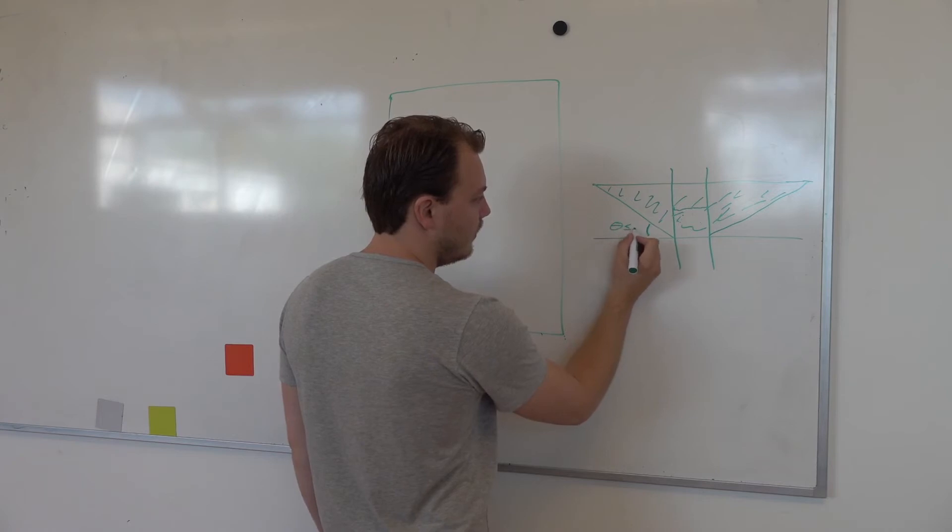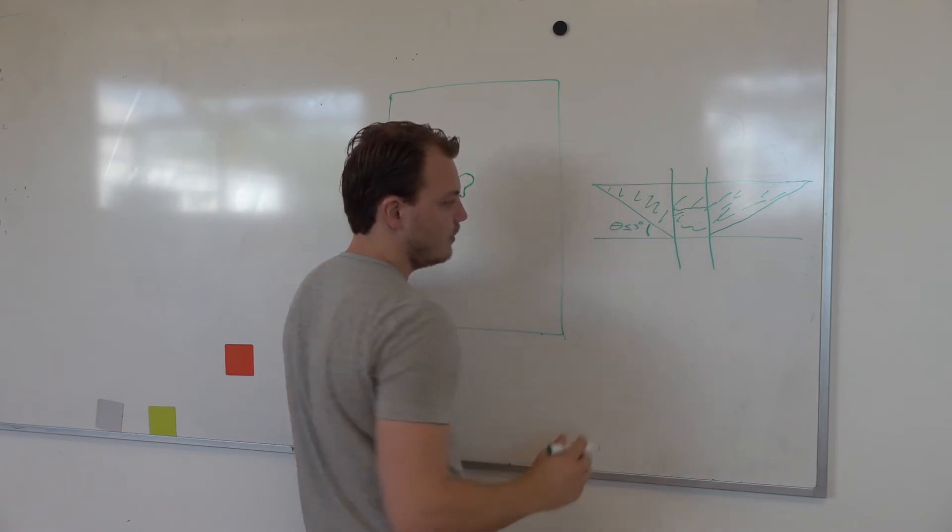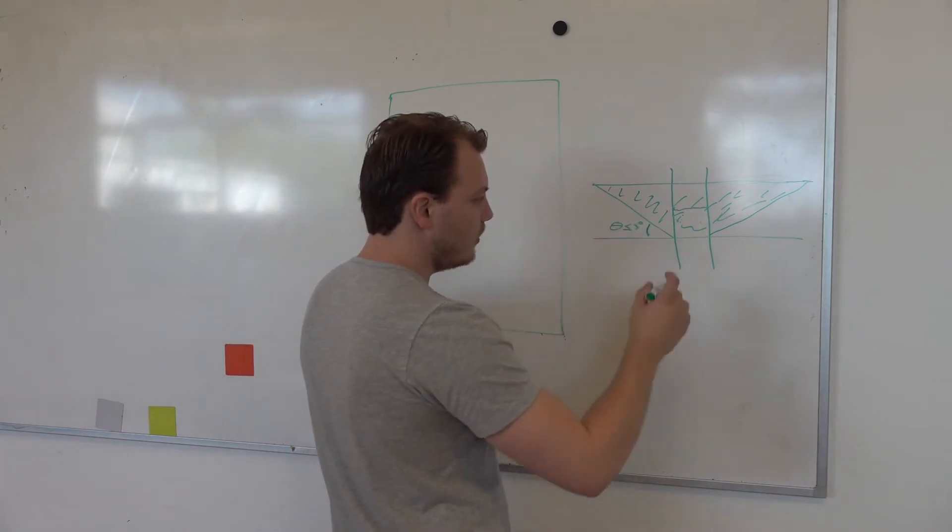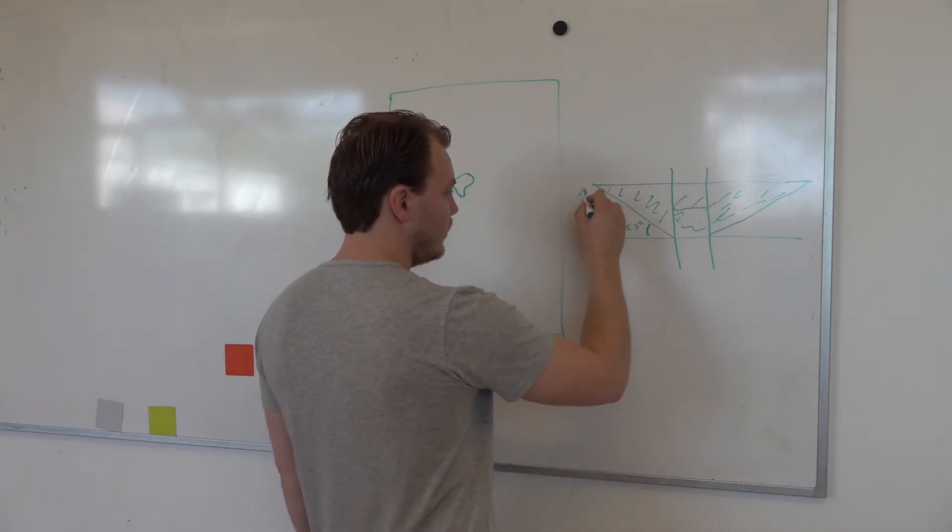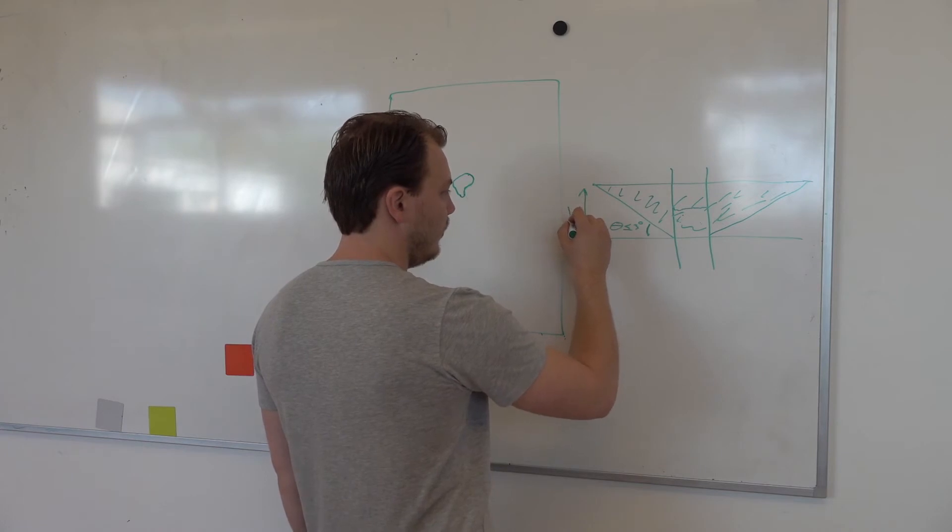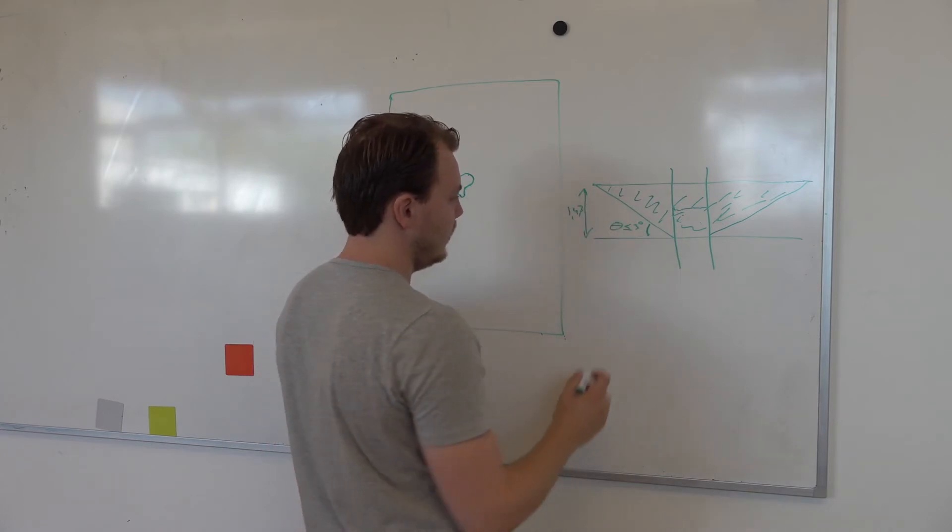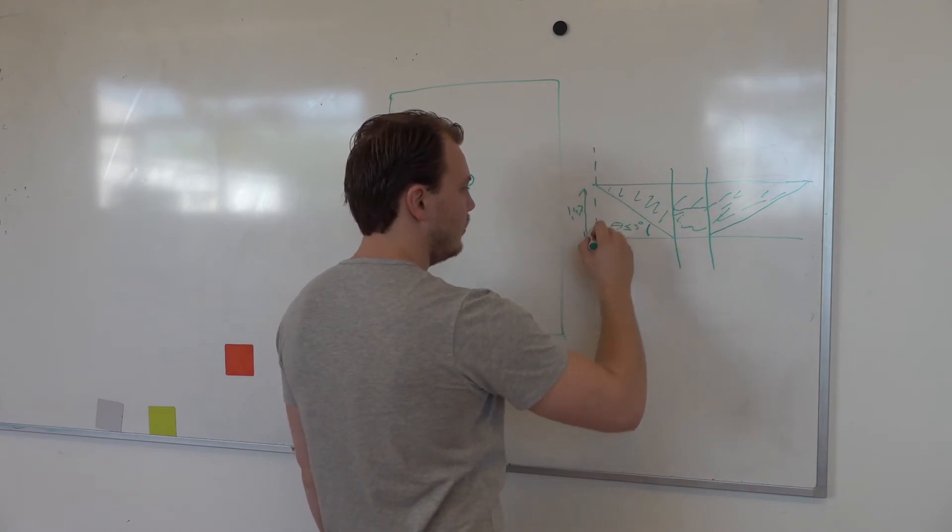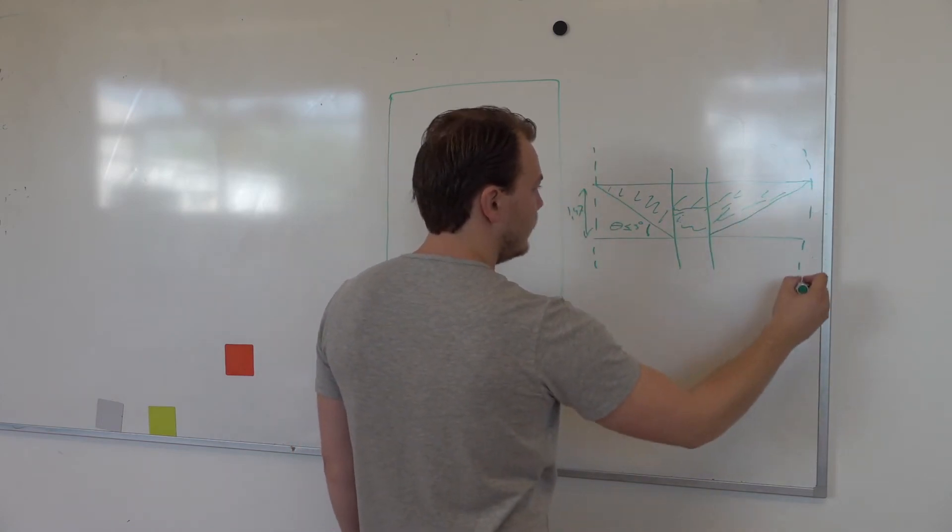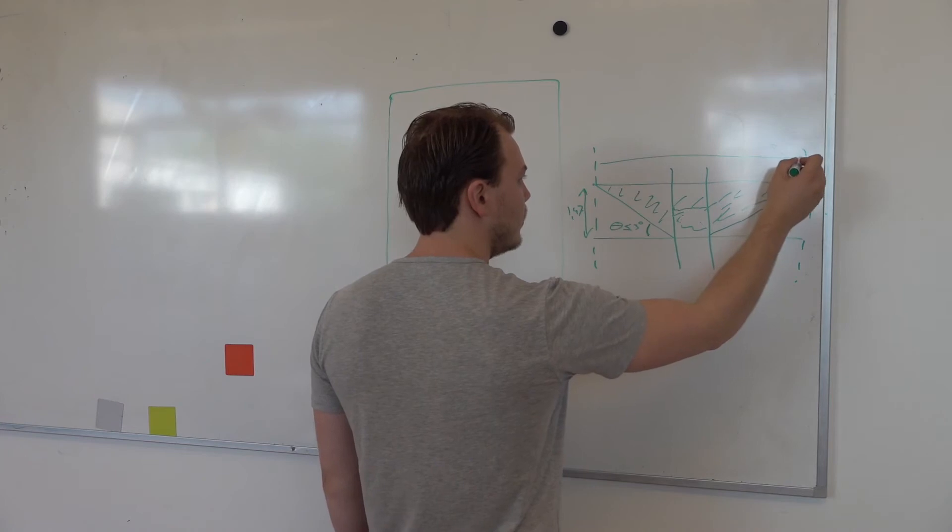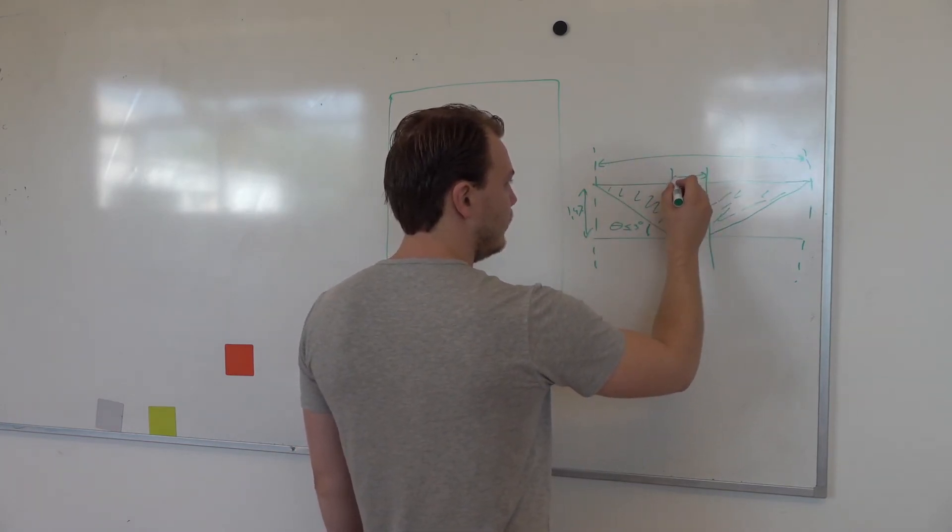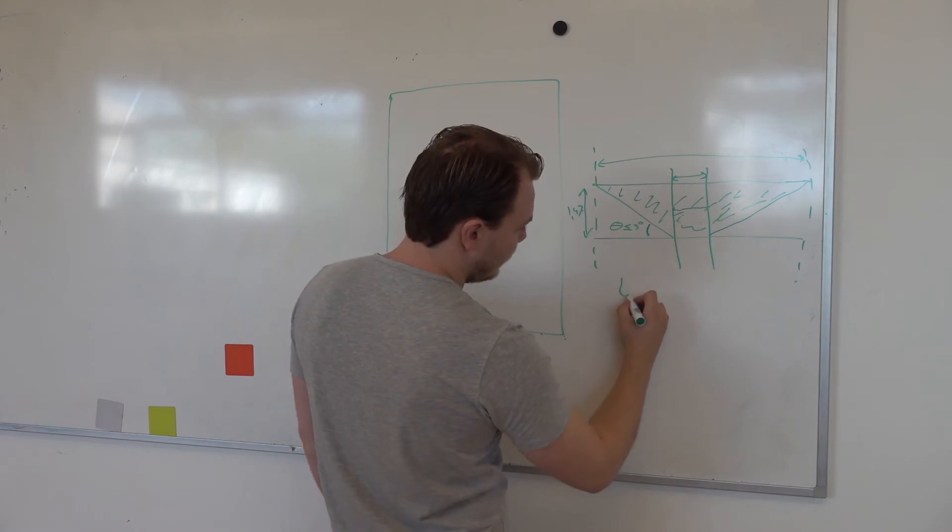This angle, especially in aerospace applications, cannot exceed three degrees. So this angle theta is three degrees or less. To calculate, we have a thickness of our laminate of 1.47 - I just measured it. So we can calculate this length of the entire repair patch.